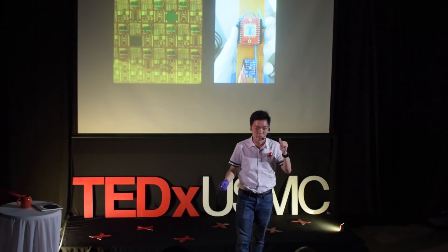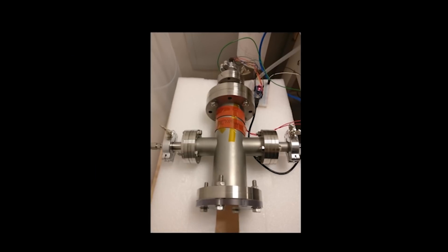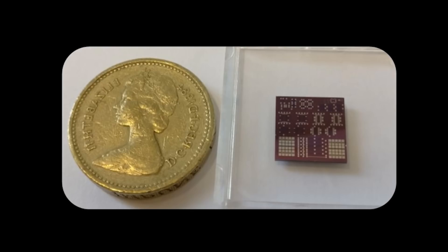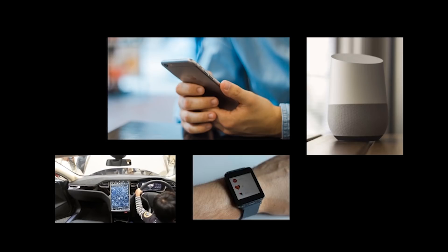This is a picture of the project that I did, and this is the setup we use to test out the sensor. All of you might be wondering why — why create a new sensor? There are sensors out there in the market, but most of them require heating in order to work, and to heat up you need power. The idea is that by using this material, which can sense at room temperature, we could create sensors that are way smaller than what we have now. One day it could even be integrated into your fitness tracker, your phone, or your everyday IT devices.